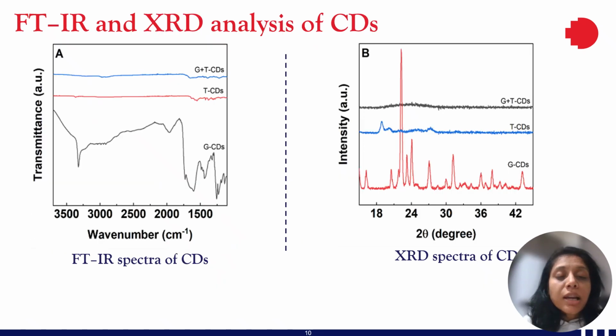Further, we went on analyzing the surface functional groups of these carbon dots and the X-ray diffraction patterns of these carbon dots. As we can see here, the glutamic acid carbon dots displayed a broad OH stretching, which was absent in the glutamic acid tryptophan and tryptophan carbon dots. This also indicates that glutamic acid did not chemically transform into carbon dots. And the carboxylic peak was also absent in the case of glutamic acid tryptophan and tryptophan carbon dots.